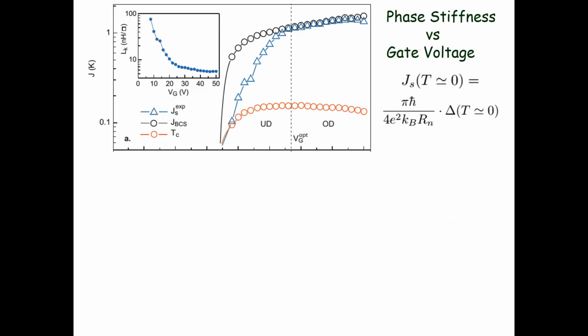All right, so what can I infer from this? So first thing I do is, this is my superconducting transition temperature as a function of gate voltage. I have the so-called dome here a little bit. So I call this an underdoped regime. This is overdoped regime, and then eventually if I make the gate voltage much higher, Tc comes down to 0. And what is this quantity here? This is the phase stiffness calculated using the BCS formula. So it rises and follows this kind of a behavior. And what is the dependence of the phase stiffness that I get from my experimental data? That is over here. And so clearly in the underdoped regime, it does not follow the predictions of the BCS theory.